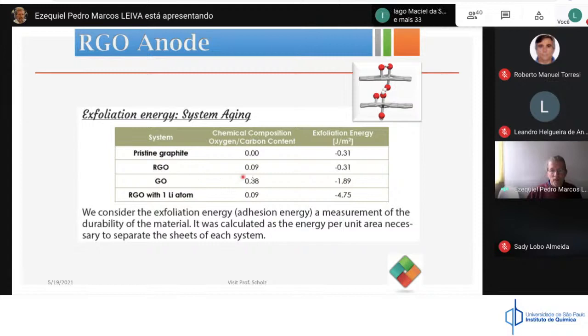You will find that in the case of graphite oxide, the interaction energy between layers is considered stronger than graphite. But the important thing is that as you lithiate, the interaction between the layers becomes stronger. That means you shouldn't be afraid of losing your material when you lithiate it, because you see that the interaction between layers increases as you put more lithium inside.